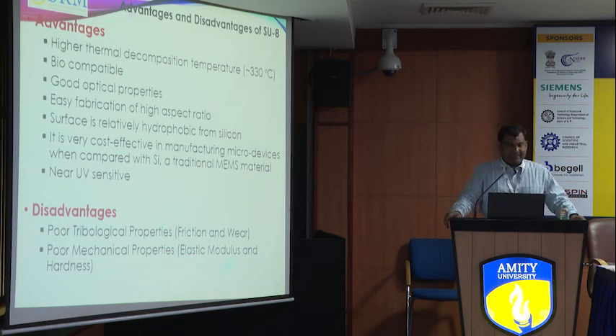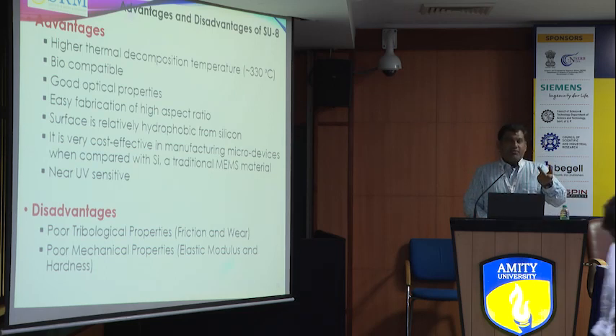So what are the advantages of this SU8 over other polymer materials? SU8 can sustain up to 330 degrees centigrade, while other polymers only 110 or 120. It is a biocompatible material, so you can also coat it on your knee or hip joints. It has good optical properties. In electrical applications also we can use it. Very easily you can fabricate within 60 seconds of UV light exposure. You can solidify SU8 immediately, but it requires UV rays. In the sun also, UV is there, so in the sun also it can solidify easily. That's why it is very cost effective, and within 1 gram or 2 grams of SU8 you can fabricate a 3D structure. That is the beauty.